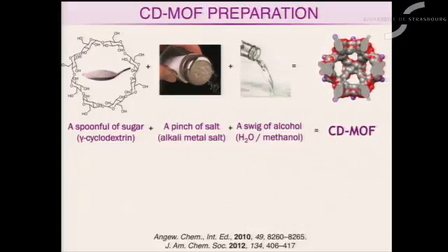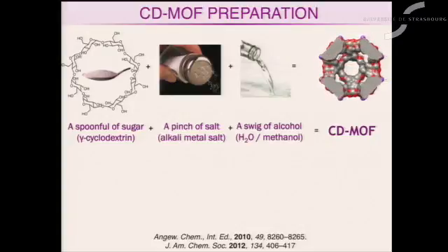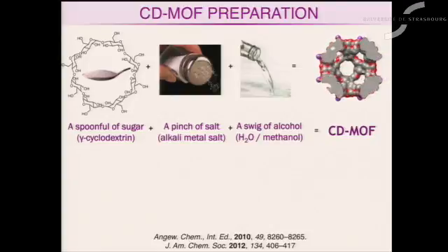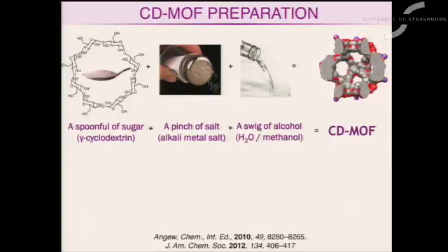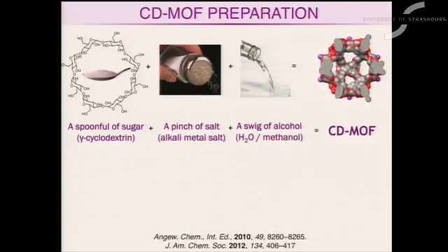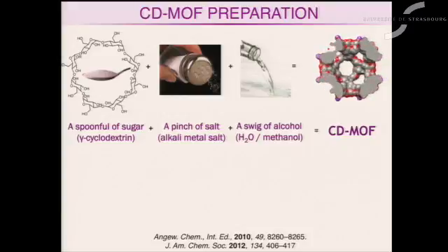And here's a slice through that shows you that we have a cavity in the middle. It's around 2 nanometers in diameter. Cavities that you see here that are circular are the cyclodextrins. They're just under 1 nanometer, and they form channels in orthogonal directions throughout the crystal, as do these triangular cavities that are between the cyclodextrins.